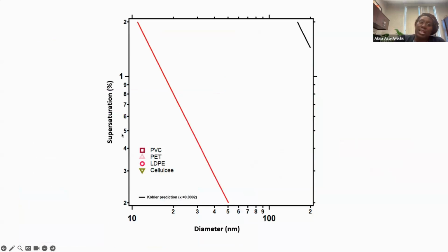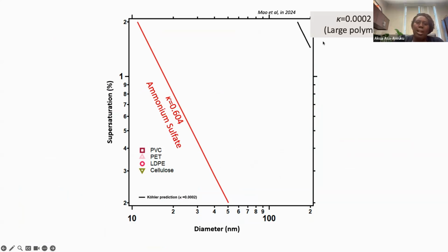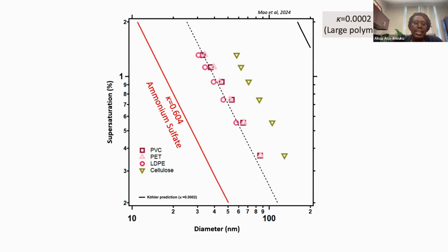In this figure, we see the supersaturation as a function of dry diameter. I've plotted here ammonium sulfate, which has a kappa of 0.6, as I mentioned, and something that's a really large polymer, with a kappa of 0.0002. How we get this large polymer is that we assume a really huge molecular weight, and because it has a huge molecular weight, it actually drives the hygroscopicity down. When we take the measurements of our LDPE, PVC, and PET with cellulose, we see it lies somewhere within this space. In fact, on average, the experimental data suggests the kappa values are about 0.5 for the nanoplastics.